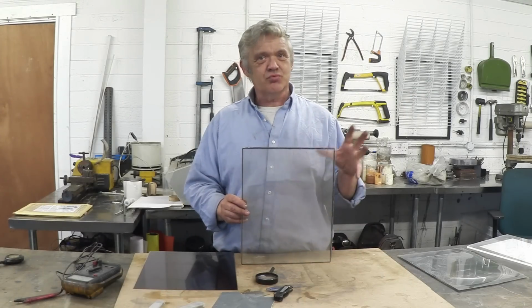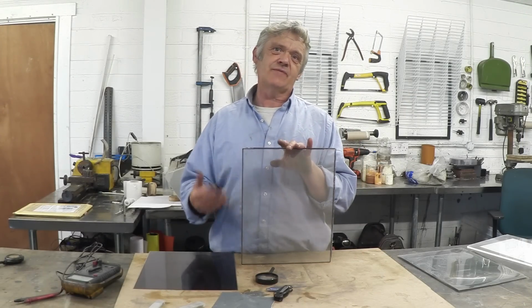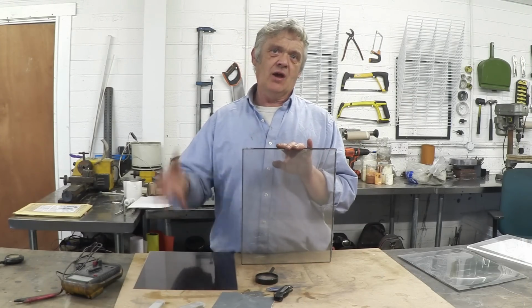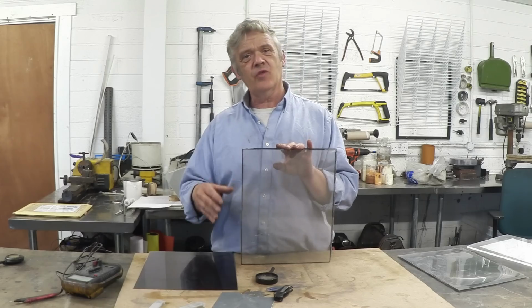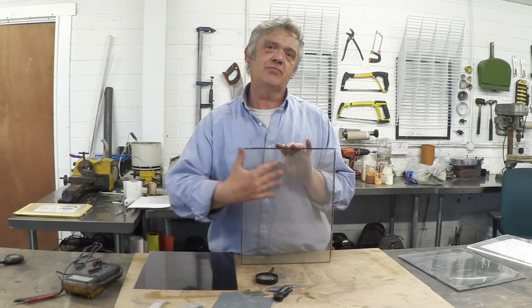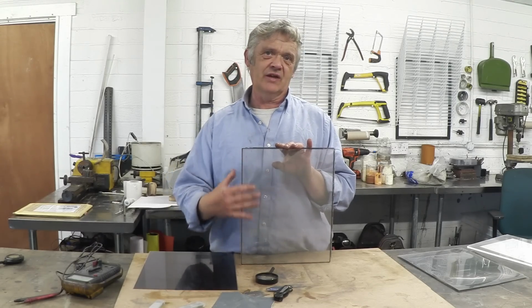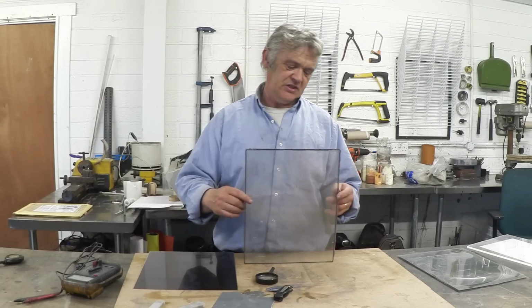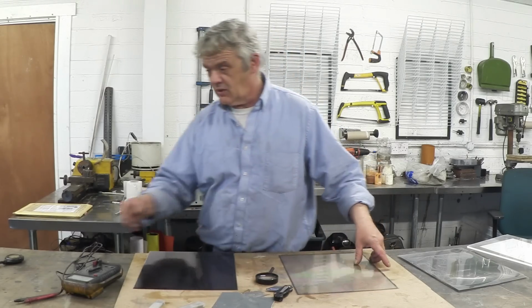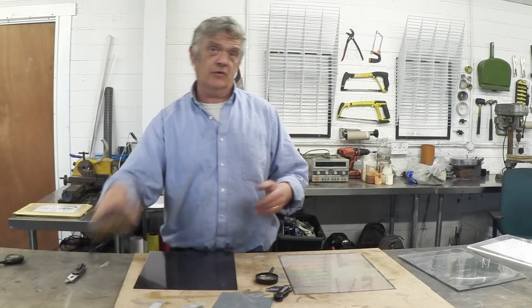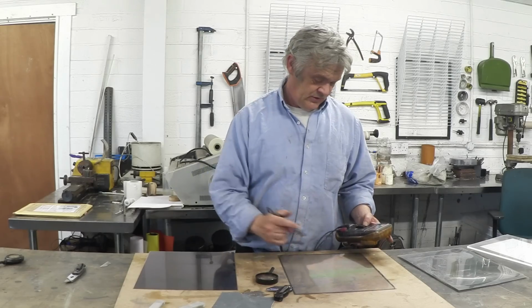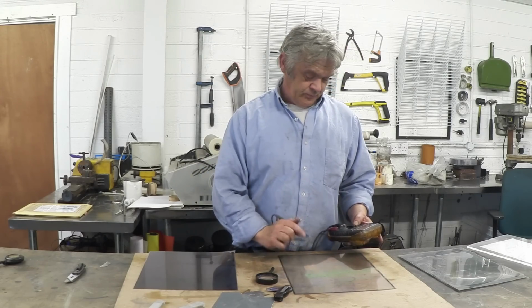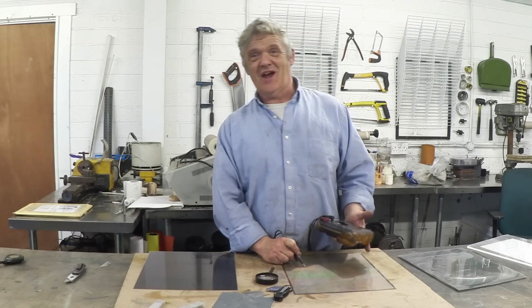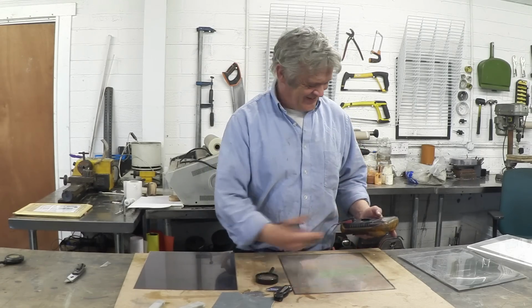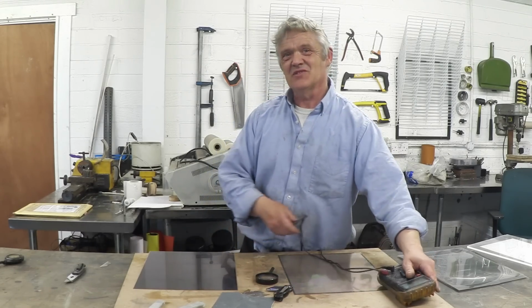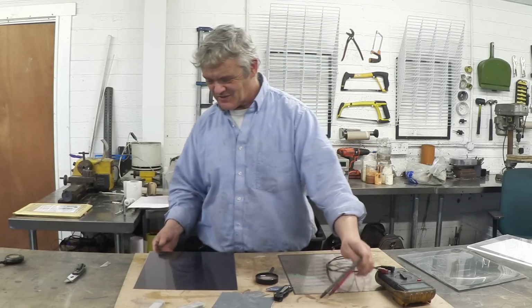As you can see, actually pretty complex, and it takes about 7 or 8 passes to place that on. And at the end of it, what they do is they put a layer of polyimide on to protect everything. So this has got a plastic layer on it. And if you actually try to take the resistance of that to see what kind of conductivity it has, then absolutely jack. You can't get that to conduct across that plane. That's obviously a bit of a shame, but that's the way it is.